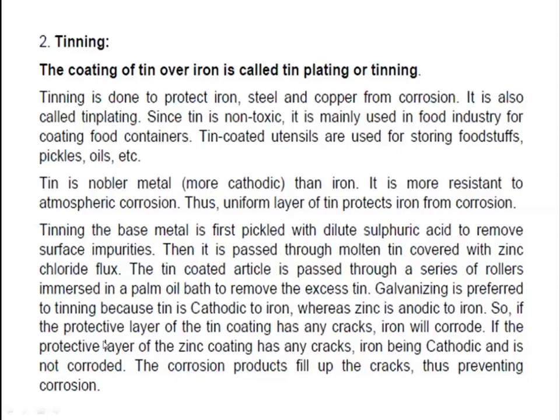Galvanizing is preferred to tinning because tin is cathodic to iron, whereas zinc is anodic to iron. So, if the protective layer of the tin coating has any cracks, iron will corrode. If the protective layer of the zinc coating has any cracks, iron being cathodic is not corroded, and the corrosion products fill up the cracks, thus preventing the corrosion.